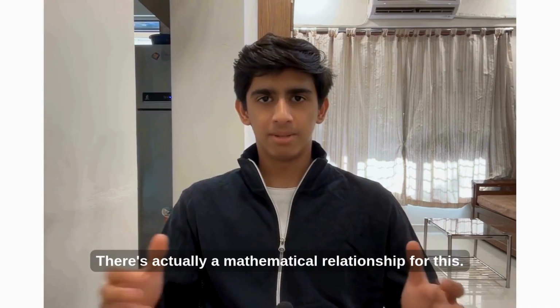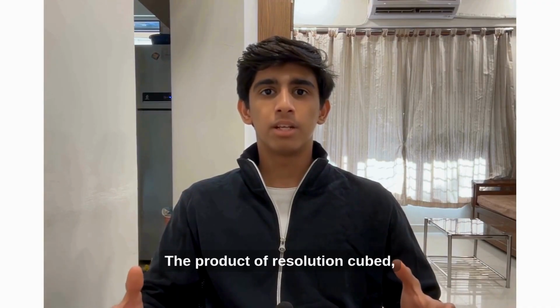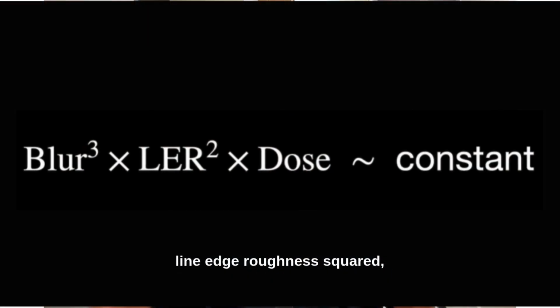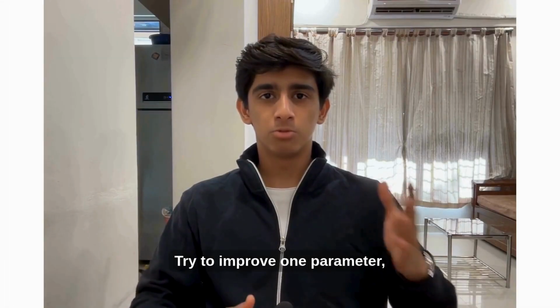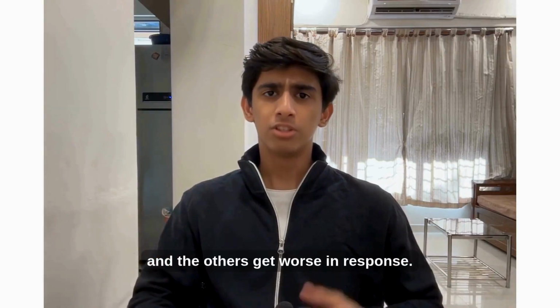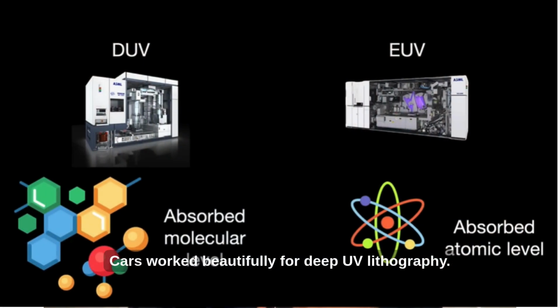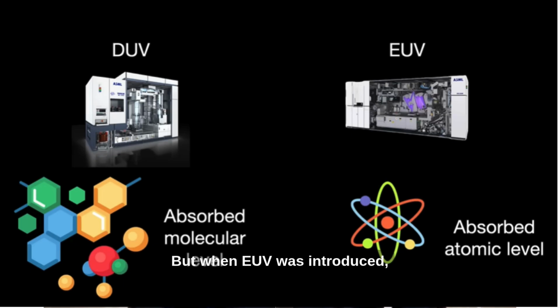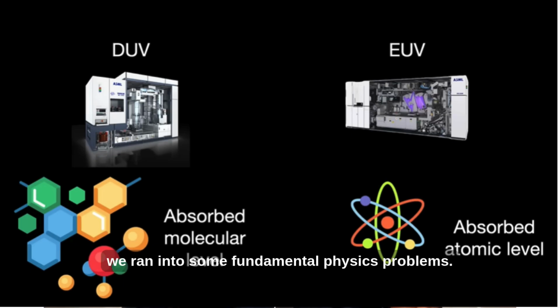There's actually a mathematical relationship for this. The product of resolution cubed, line edge roughness squared, and dose to size is constant. Try to improve one parameter, and the others get worse in response. CARs worked beautifully for deep UV lithography, but when EUV was introduced, we ran into some fundamental physics problems.